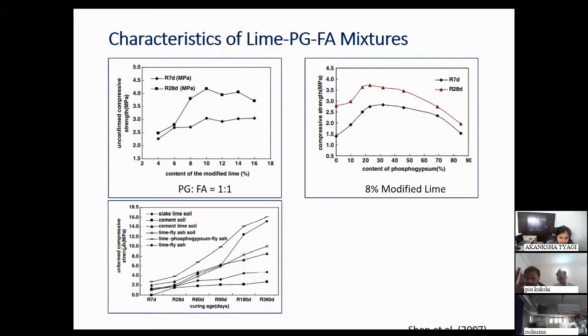And when they compare it with the other conventional admixtures, like this is the cement soil, this is the slake lime soil, and this is the cement lime soil, this lime phosphogypsum fly ash is found to have the highest strength as compared to other conventional admixtures. And like lime fly ash. So you see, this is the lime fly ash, and the lime fly ash phosphogypsum has very high